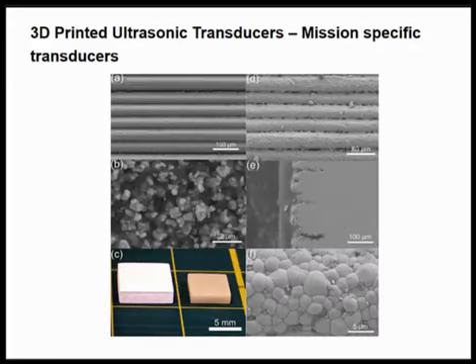I should start with C actually. You get this nice green body, so this composite at the end of it, which is our ceramic particles embedded in our polymer matrix. That's the SEM of the nice well-dispersed particles there. That is about 3 months' work to get to that point, to get the resin behaving quite nicely so that it's fully dispersed. But to start, you think it's going to be easy, just put particles in a polymer matrix.